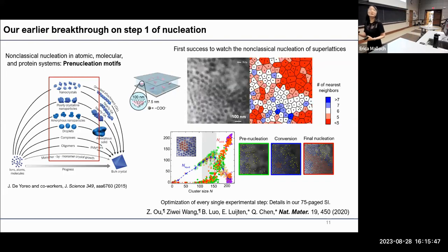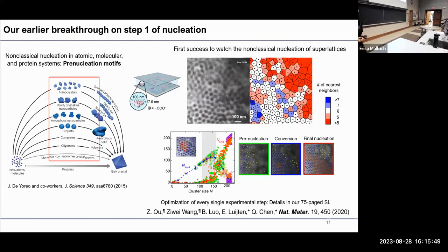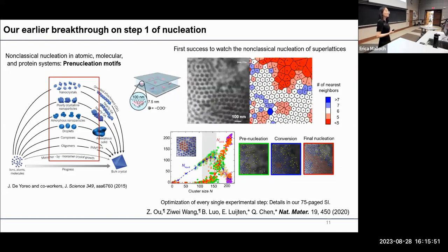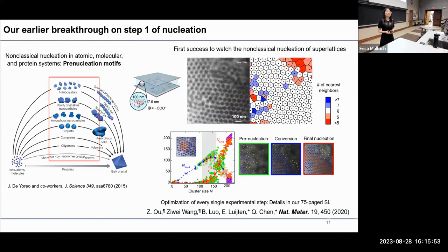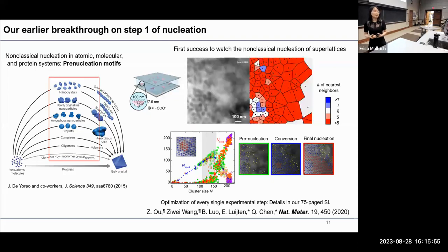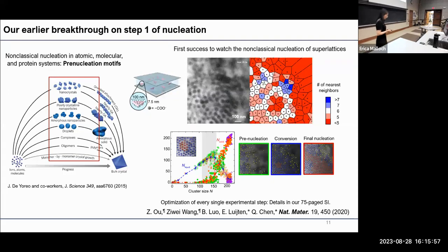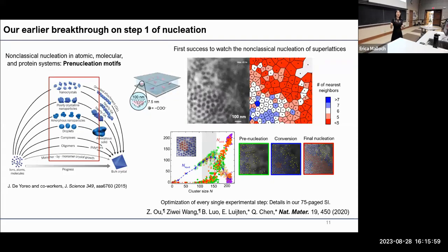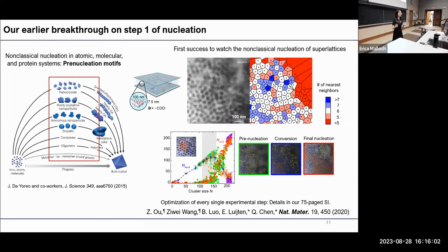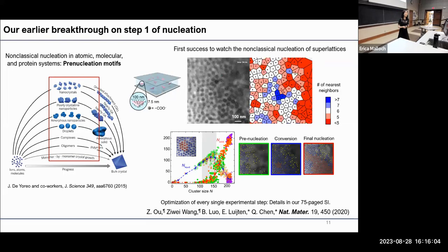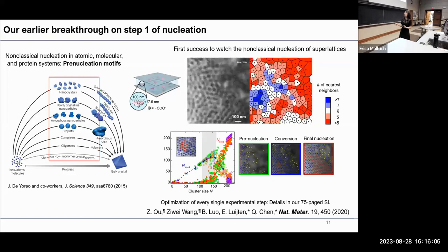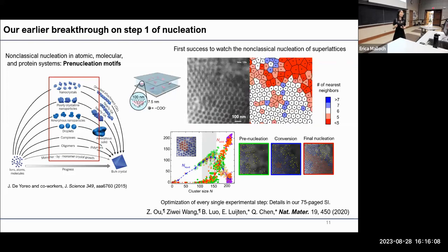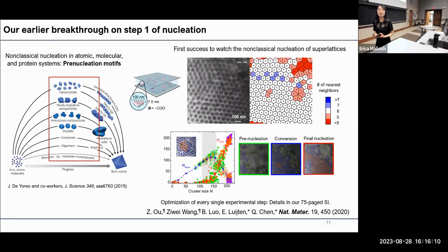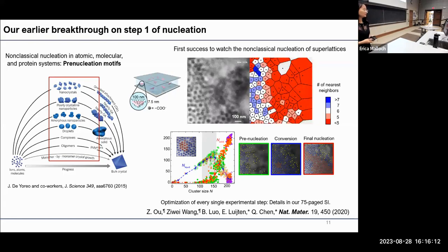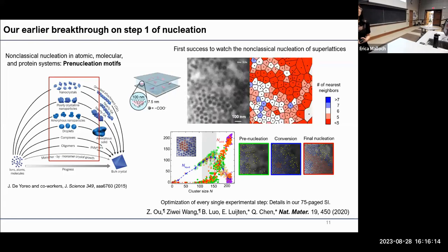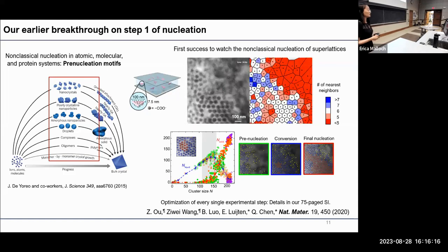This is a nonclassical mechanism that has been demonstrated in atomic, ionic, protein, and molecular building blocks, and we show it for the first time for nanoparticle building blocks. I also want to mention that in order to capture such movies in a quantitatively robust manner, we need to optimize every single step of our experiment, which we included in the 75-page supporting information of this paper. So this concerns nucleation, which is the first step of crystallization.